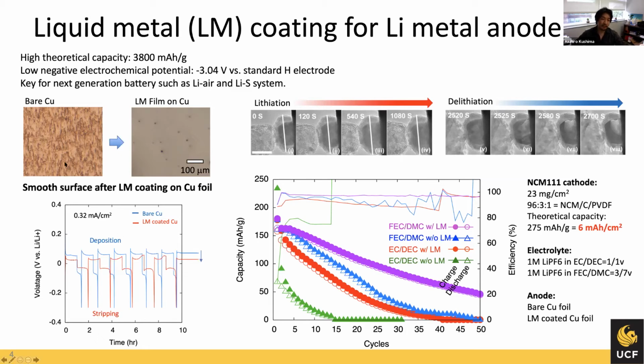So if you try to deposit lithium, you can decrease the overpotential. Here, with and without the liquid metal coating, you can significantly lower the reaction overpotential from the blue line to the red line. So you can easily spread the lithium on this coating.